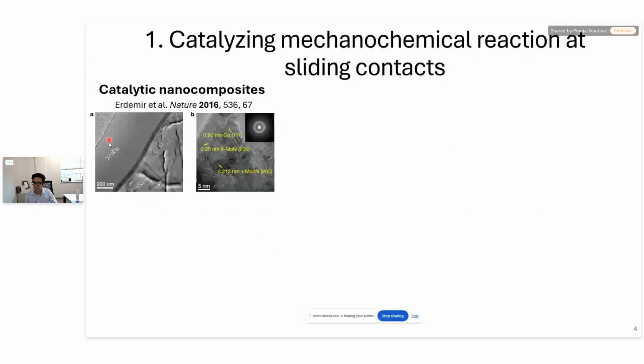So as you can see, they applied a coating of these nanocomposites on a steel substrate, and then they conducted wear tests of these coated surfaces. They observed that these coatings resulted in negligible wear of specimens, as opposed to steel surfaces, which under identical conditions experience tremendous amount of wear.